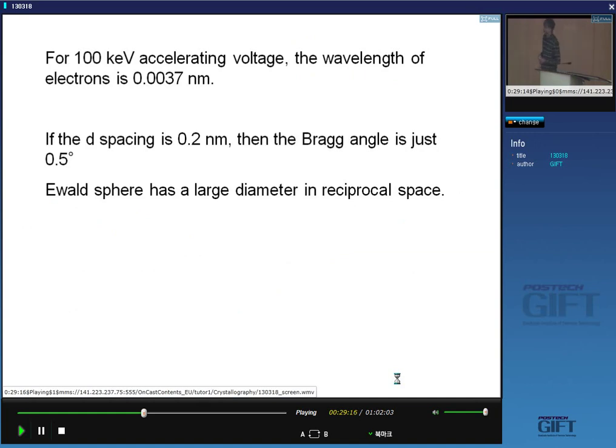Now, just to give you an idea of the wavelength of electrons, the typical accelerating voltage in an electron microscope is about 100 kilo electron volts. The wavelength would be very, very small. Okay, so that's 0.0037 of a nanometer. And if the typical spacing of planes in a crystalline material is 0.2 nanometers, then the Bragg angle is very, very small, half a degree.